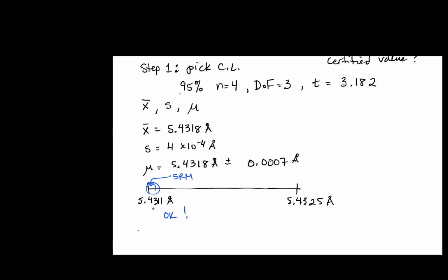The important thing is that the SRM is inside my confidence interval. And if that's the case, then my conclusion is that my instrument is giving me statistically equivalent information to the standard reference material, which means that my X-ray diffractometer is calibrated.